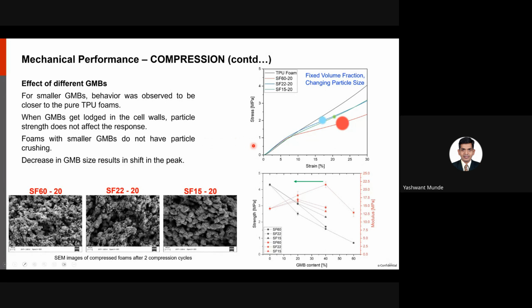So focusing more on different GMB sizes, we fixed the volume fraction at 20% because we saw very good properties at that small volume fraction. We see that as we reduce the particle size, the response gets closer to the original TPU. As you can see here, the gap is closing. This is because, especially for the strength, the particles are all embedded within the cell walls. So first, the walls of the segregated region have to come in contact, and only then will the particles embedded in the walls start to get stressed and try to collapse, which maybe they won't even collapse because of the extremely high collapse strength of the smaller particles compared to early crushing of the larger particles.